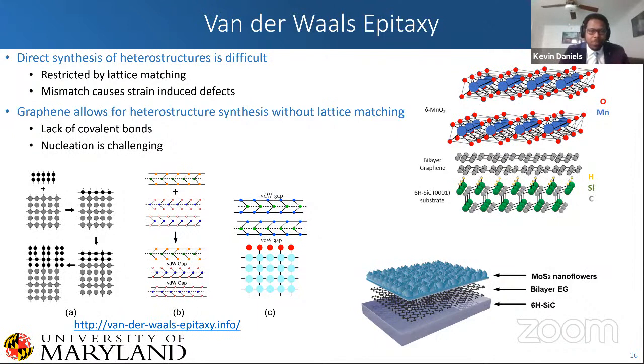The issue is nucleation, which can be very challenging, because if you're not binding the crystal to the substrate, then it really needs to figure out the template for which it needs to form. And so, I'll show later ways that we are able to create at least a faux template for some of these materials by electrochemistry.